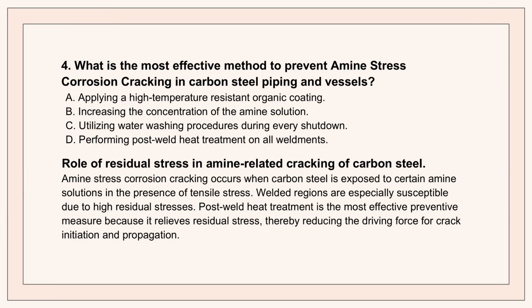Okay, so now let's combine stress and chemistry. Our final structural mechanism is amine stress corrosion cracking, or amine SCC. Right. This is failure driven by residual tensile stresses, especially in weld areas when they're exposed to amine solutions. This one is a huge problem, but the prevention method is, well, it's absolutely critical. The most effective method is performing post-weld heat treatment, or PWHT, on all weldments.